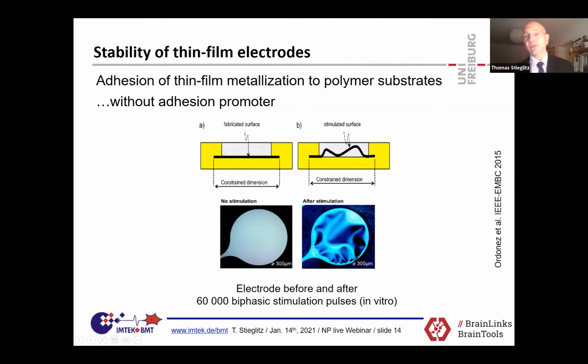Some electrochemistry takes place, and you have a kind of popcorn effect, and you get those bubbles, and if you touch them, they'll break, and your electrode is gone. And this has been, over the years, one of the largest challenges: to make that very thin layer stick to the underlying substrate, so that it does not get destroyed. And this is something that you do not see in your first round of acute experiments where you get excited, you know, putting that for an hour in a rat is awesome, but doesn't show you the problems. The problems show up after 6 months, 8 months, 10 months, or something like that.